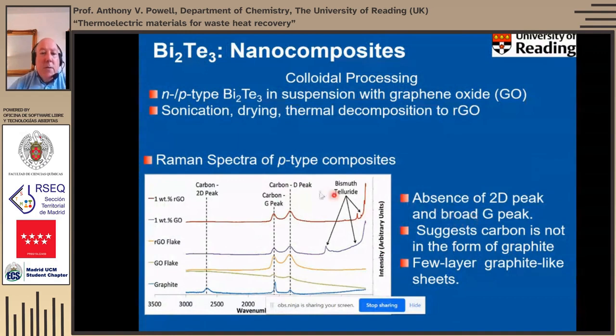And we can follow that process using Raman spectroscopy. So this curve right at the very top here, for instance, is a 1% reduced graphene oxide bismuth telluride composite. The important thing to note really is that this carbon 2D peak, which is present in graphite, is not present in the composite. And also this carbon G peak, which is very sharp in graphite, is broadened considerably. And you'll notice the intensity ratios of these two peaks have swapped around. So all of those factors together suggest that we don't actually have graphite there. We don't really have graphene there either, as far as we can tell, but we probably have few layer graphite-like sheets. So it's somewhere between bulk graphite and single layer graphene.